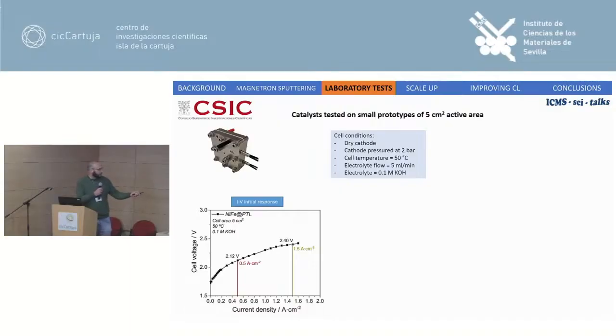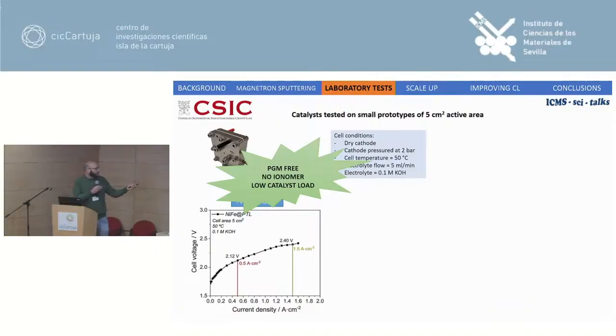These two values that I have marked are standard values in the literature for different current densities. They are more or less the average value for this kind of formulation prepared by wet routes, but with the particularity that we have a PGM-free catalyst, no ionomer, and our amount of catalyst deposited by this technique is very low. So we have 3 advantages compared with the catalysts that are normally prepared by wet routes in the literature.